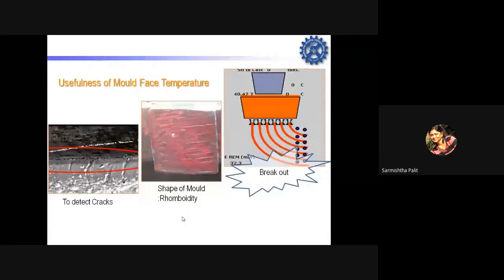This mold temperature basically gives the property of the billet or the slab which is coming out. There could be very fine cracks which you have to avoid, and that is because of the temperature within the mold. The shape can also change: a billet is a square, but that square could become rhomboidic. Another problem is the breakout, because many times it solidifies before coming out, and that creates havoc. You have to clean it and stop the production, and that takes a minimum of 6 to 7 hours. So there is a huge production loss.